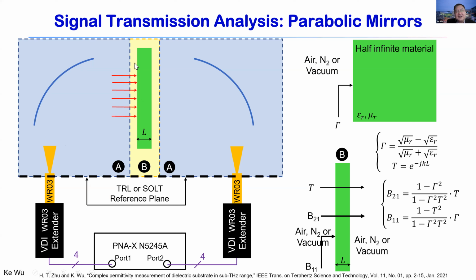So this is important for the so-called system efficiency measurement prior to the actual measurements. For terahertz, one of the most important things we need to do is to create a very high efficiency, low loss transmission for this quasi-optic free space measurement. Which means all the power should not be wasted in the space. Everything should come back or be transmitted to the system.